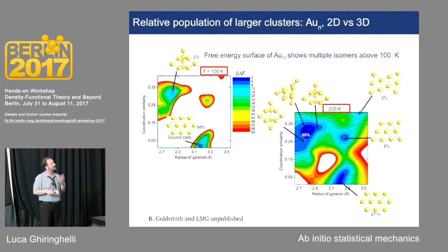We just looked at how many different clusters were present after the simulation. So the similarity is by looking at how many atoms are two-fold, three-fold, four-fold, and five-fold. So you get a histogram of the population of the different coordinations in the cluster. And a histogram can be treated as a vector, so you measure distance between vectors where the reference is the lowest energy cluster of this size that was found during the simulation.